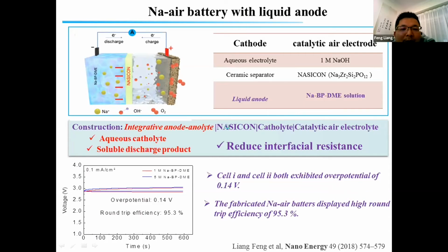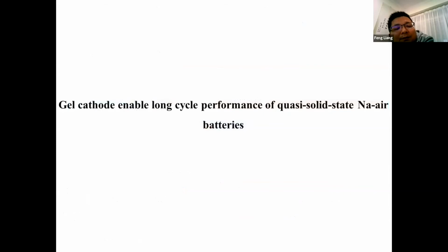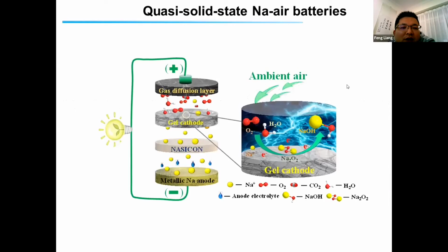But as we know, in the case of the hybrid sodium battery, the evaporation of the aqueous electrolyte is a big challenge. So therefore, recently we use the gel cathode to prepare the quasi-solid-state sodium battery. By using this gel, this battery can be cycled for a long time. So this is the structure of this battery. Here is the gas diffusion layer, and this is a gel cathode. And then NASICON, and here is the metallic sodium. So it can work in real air